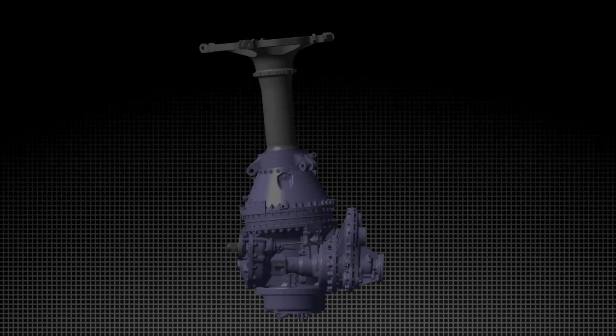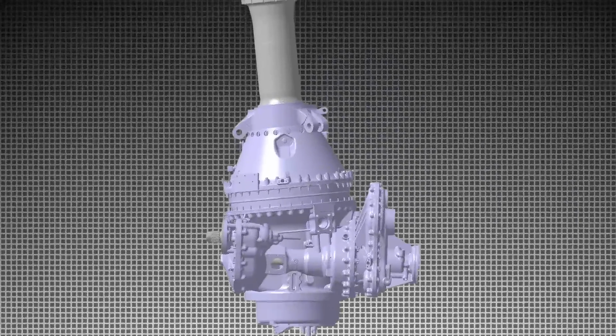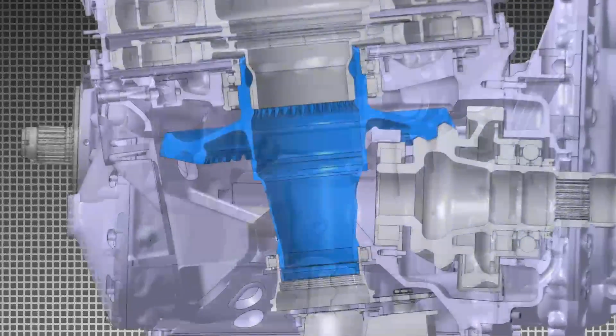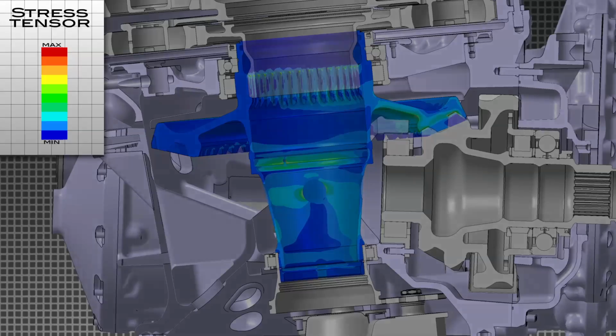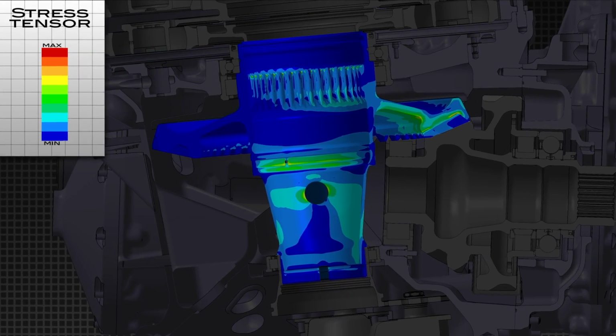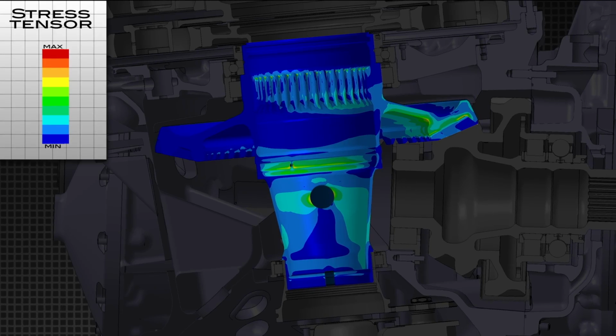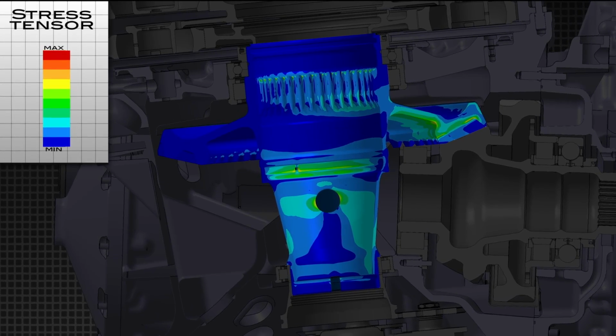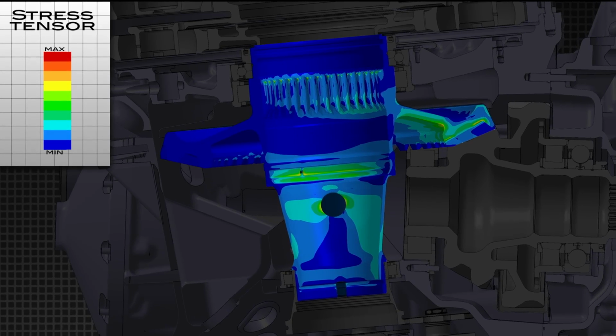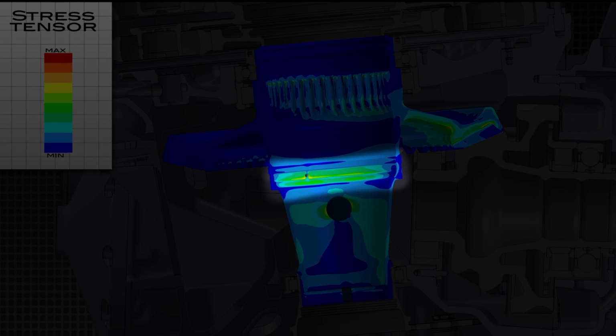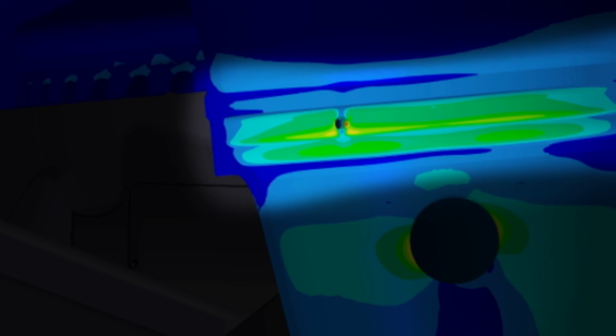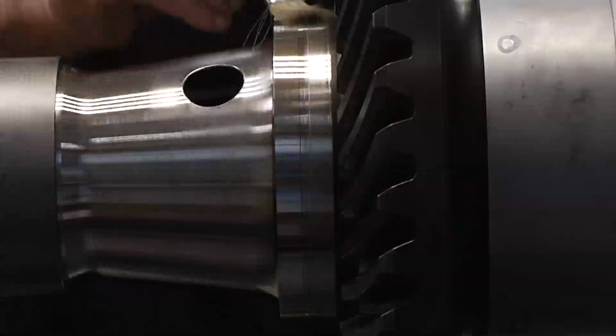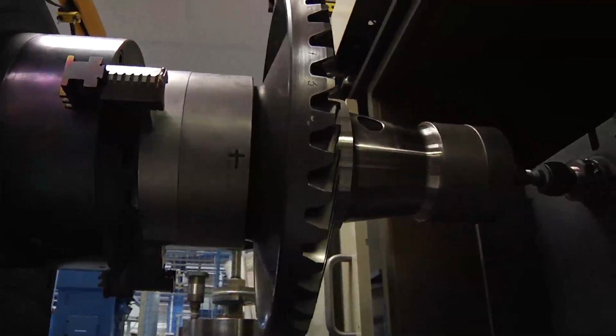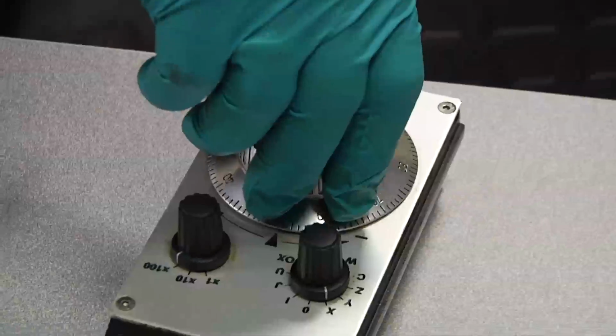Factor 1 and 2. Residual stress and hotspots. Many parameters influence a part's resistance and its safety margins. The geometry, the material, heat treatments, production process, flight loads, and any alteration that could occur all along the life of the part. In particular, residual stresses resulting from the welding process contribute to reduce the fatigue strength in this welding area of the main gearbox bevel shaft.